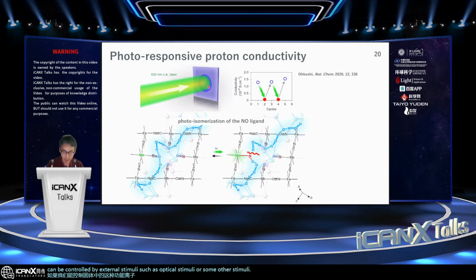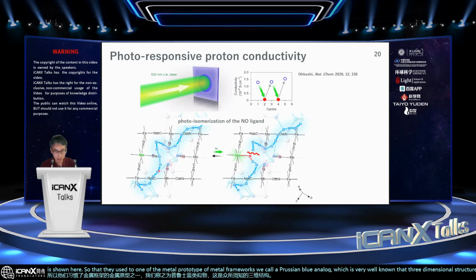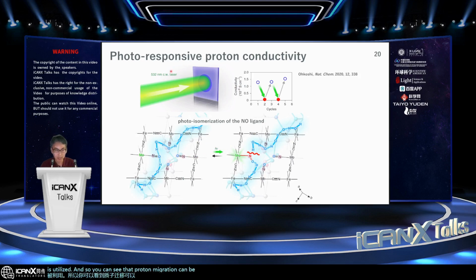this is very important from not an electronics, but more an ionics viewpoint. This is not our work, but one example from 2020 is shown here. They used one prototype of metal organic frameworks called Prussian blue analog, which is very well known. The three-dimensional structure is utilized, and you can see that the proton migration can be switched on and off by light. The key was that this NO moiety can be switched on and off, which contributes to forming the extended proton conducting pathway or not.